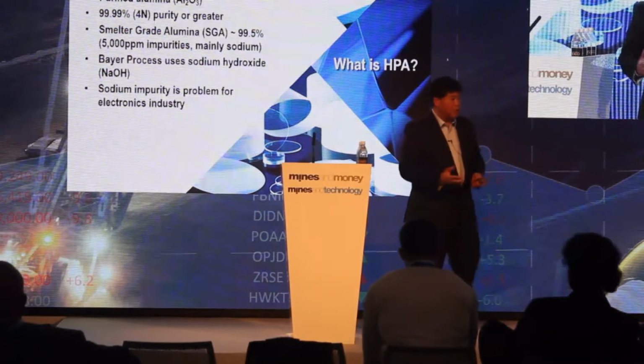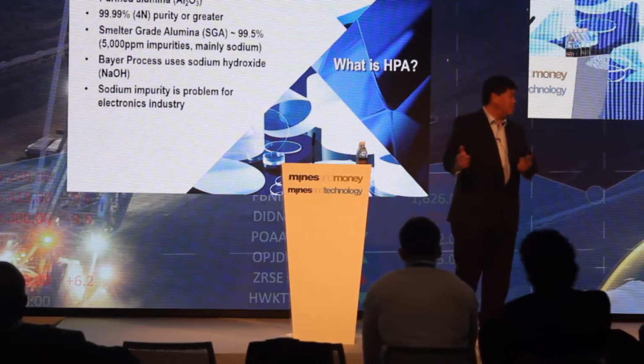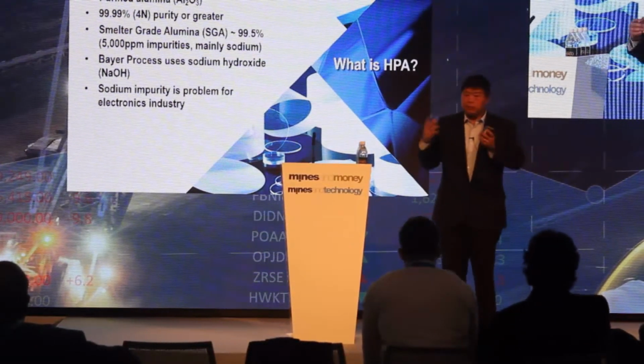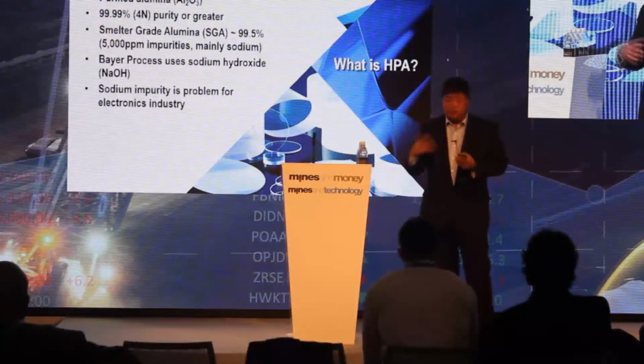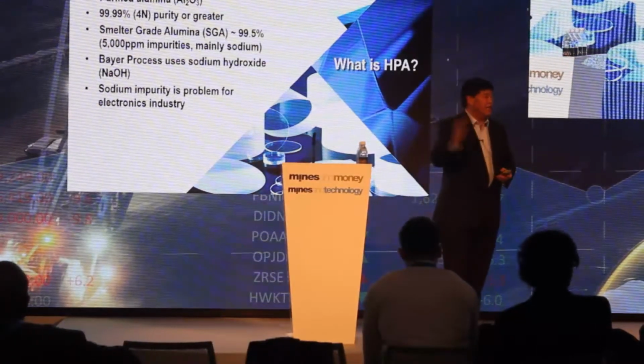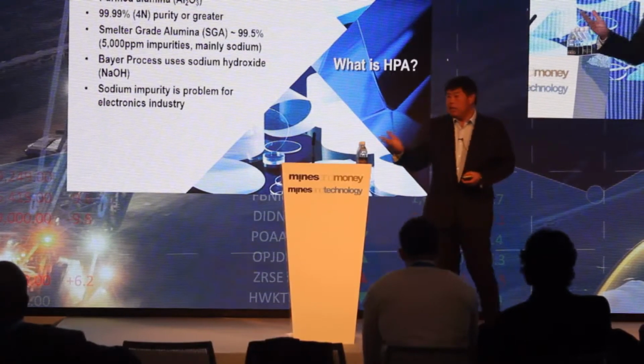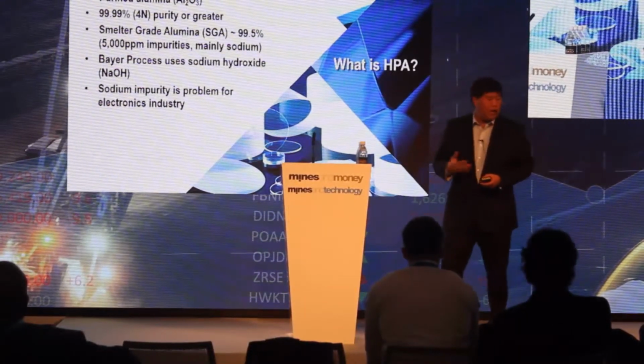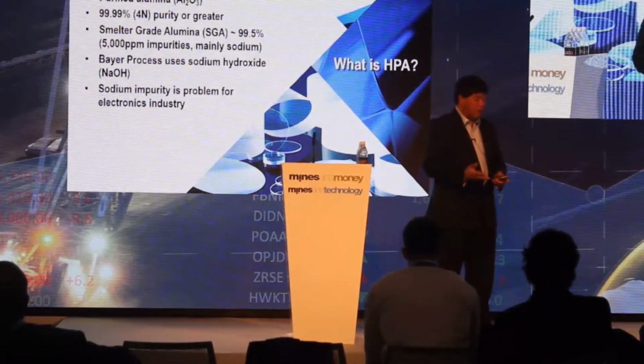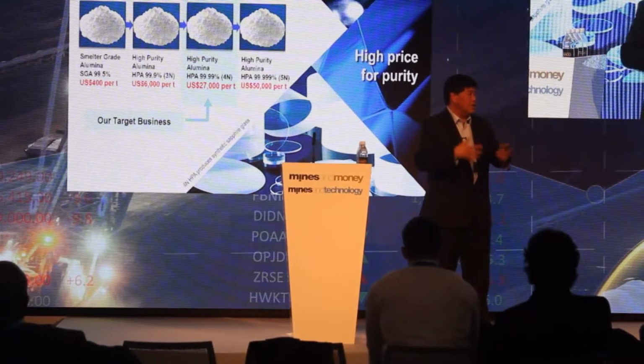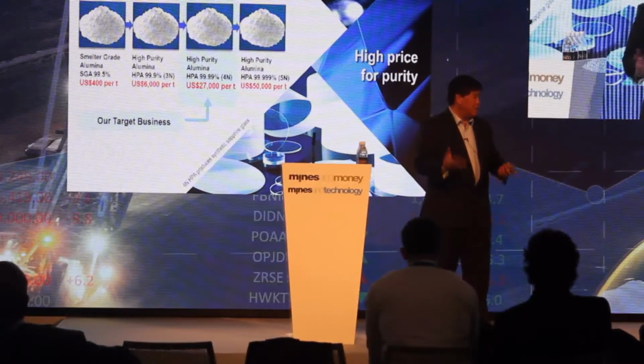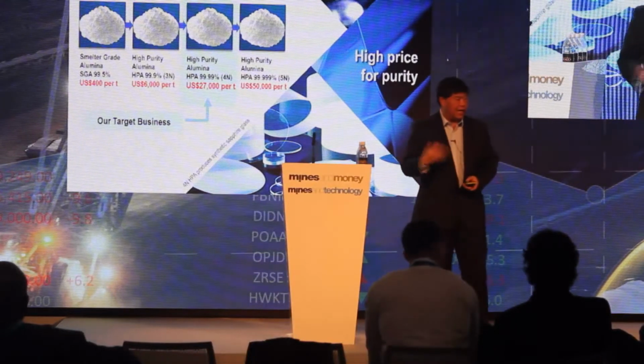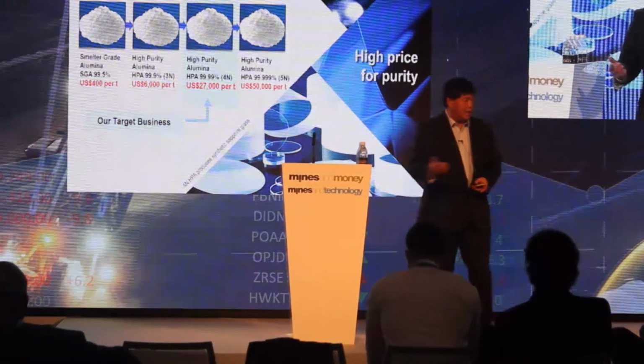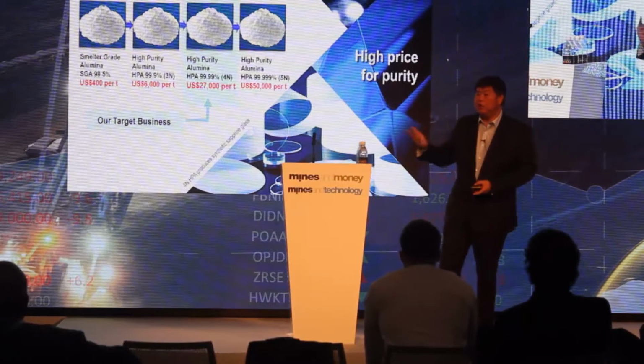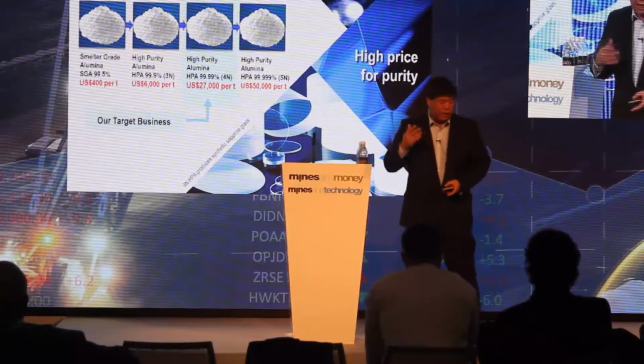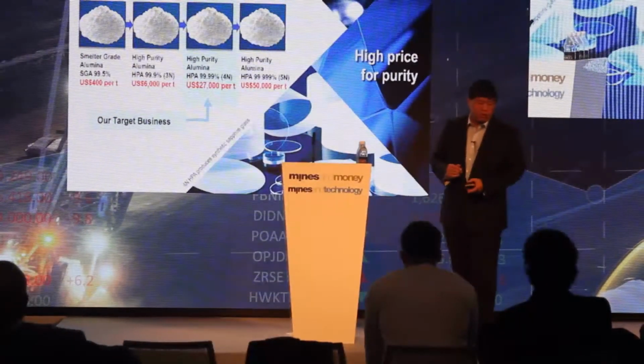And this material that we want to produce is 99.99%. It is comparable to the smelter grade alumina, but it has another 2 nines. But the price of this material, instead of $400 a tonne of smelter grade alumina, is $27,000 a tonne. So it's a high value material. And this is typical of high purity materials. As you go up in the quality, the price is exponential.